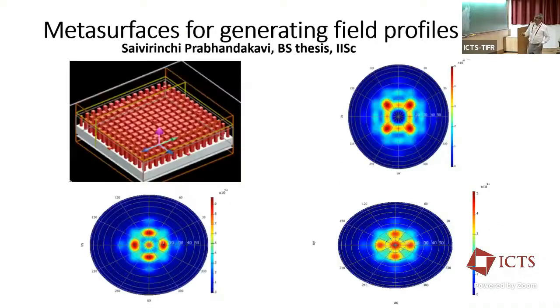So we moved on to a metasurface based one. These are square cross-section silicon rods, whose dimensions are chosen in such a way that the phase of the incident beam is manipulated. Initially we had 4 beams, with feedback from RCI we made it into 5 beams, and modified it further to get equal intensity beams at about 3 mm from the surface of the sample. Right. So we made the first set of samples. We want this to be tested.